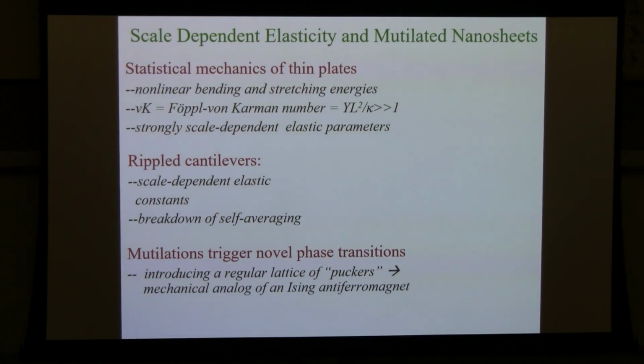But I want to convince you that there are important circumstances where, in fact, the elastic constants themselves become scale dependent. And they depend on the system size in a very surprising way, and it's often a very strongly system size dependent effect. So I'll start by talking about the statistical mechanics of thin plates. The classical zero temperature theory goes back to 1904 and work by Foeppl-von Karman.